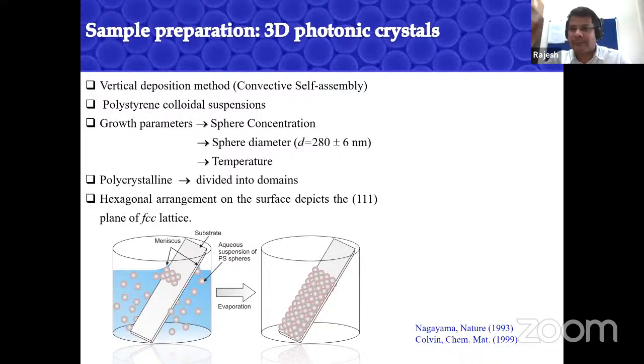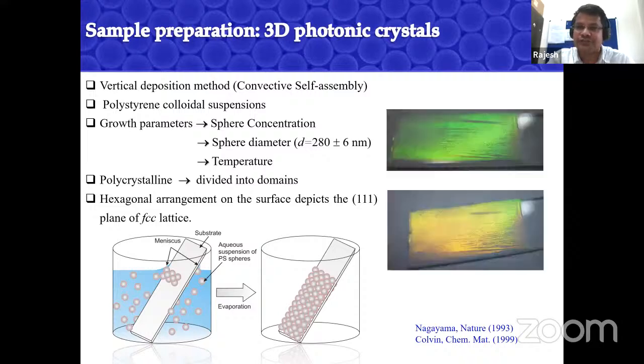So once the sample growth is done, you take the sample from this beaker, and the sample will really astonish you. The sample looks like this. If you put the sample in the tube light in the laboratory, it nicely diffracts the light. And this color you see is because the sample is reflecting around green light, which is a band gap for this sample. So the green light cannot go into the system, so it is reflected back.